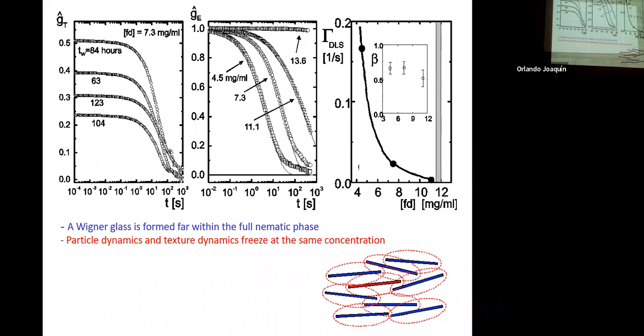And the reason lies in long range electrostatic interaction, because at low salt levels, when you increase the concentration, you diminish the extent of the double layer, and at some point they do not form a glass anymore. So the glass transition is really due to long range electrostatic interaction, and that is called a Wigner glass.